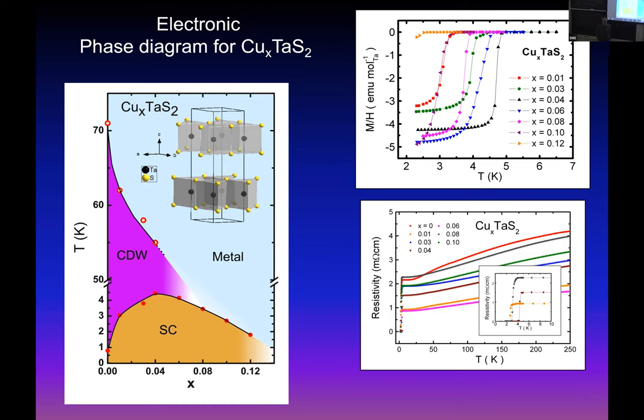So copper in between, like at 0.04 coppers per tantalum, think about what that copper layer is in there. It's only 4% of the holes are filled with copper. So they're far apart. So it's not a copper-copper conductor. The copper has donated its electrons to the tantalum disulfide layer. And that donated electron that's gone in there has yielded superconductivity. So that's suppress the charge density wave and give the rise to superconductivity. So basically, the spontaneous ordering of the electrons has been disrupted by changing the electron count. After disrupting, you've got a superconductor.